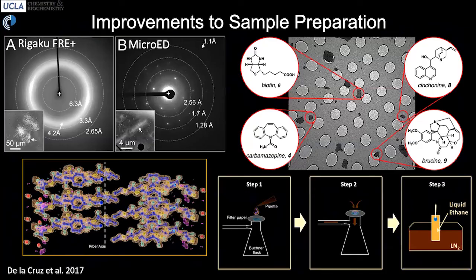And so one of the things that we're really excited about is being able to tackle samples that might not be pristine, that might not form pristine crystals. Of course, if you're able to form large pristine crystals, you might just take your sample to the local X-ray diffractometer and collect a conventional X-ray diffraction data set. But if you have highly polycrystalline samples or crystals that are present in heterogeneous mixtures of amorphous and crystalline phases, we're really interested in developing methods to more routinely determine structures from those.